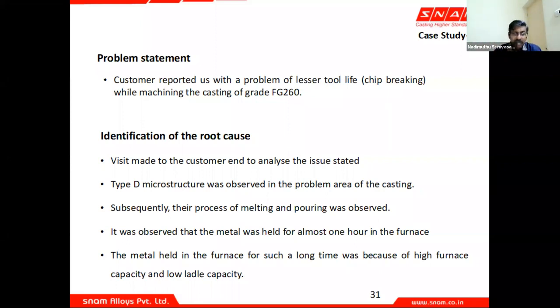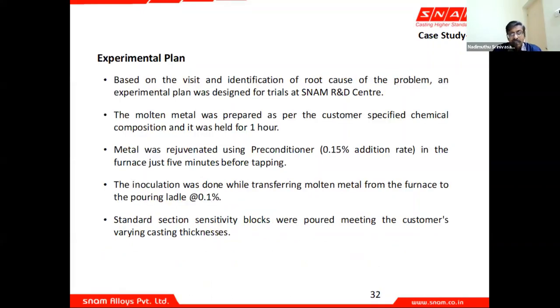Now, when we went here, we took some material and we found that the metal was being held for more than 1 hour. So we wanted to add some pre-inoculant, but we were given only one condition: right now we have all these issues. Our production is going on. We cannot stop it. You do one with just preconditioner, one with just our inoculant. We had the thermal analysis equipment with us. You take the readings, then you go back. You have the R&D center foundry. You can do your trials and then come back to us. And that exactly is what we did. So based on whatever we had taken there, we did a root cause analysis and designed an experiment at the R&D center.